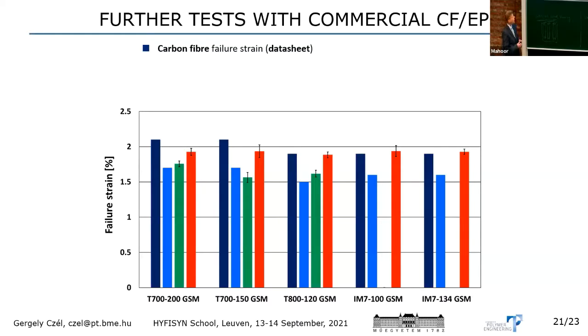And then finally, we thought that, okay, these materials which we used so far, these TR30 and TC35 carbon fibers, especially in a thin prepreg made by a random Korean company, might not be of a lot of interest to people who we want to convince. So why not do some tests with commercial carbon fibers used by Boeing and Airbus and big companies. So we took Toray T700 and T800 materials and Hexcel IM7 carbon fibers, and I took the failure strain, the UD failure strain from the datasheet. That will be the darker blue